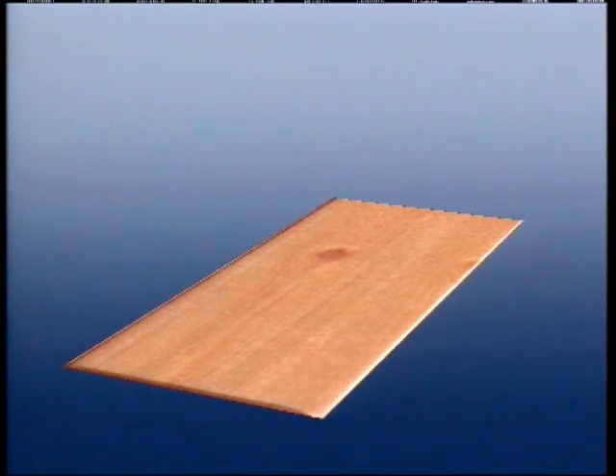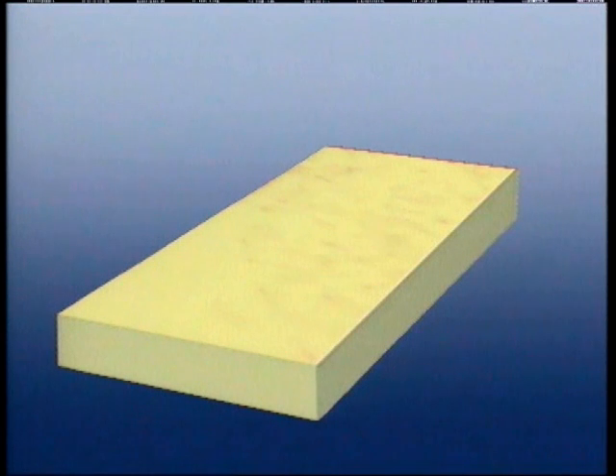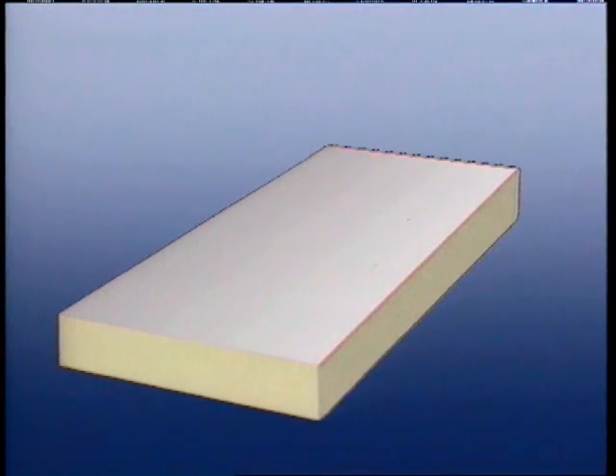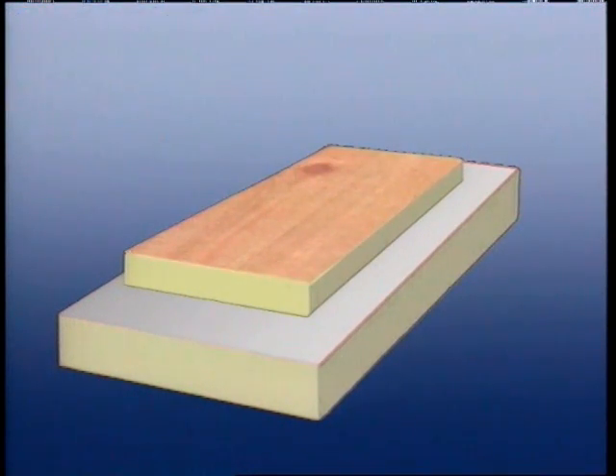The flat panels are prefabricated by the successive piling and bonding of a 9mm thick plywood board, a secondary insulating layer 160mm thick made of glass fiber reinforced polyurethane foam, then bonded again onto the upper side, an aluminium glass cloth composite material sheet serving as a secondary barrier, the primary insulating layer previously prefabricated by bonding reinforced polyurethane foam and 12mm plywood. The thickness of the primary insulation is 80mm to give a final panel thickness of 250mm after assembly. The panel boards are next machined to their final dimensions.